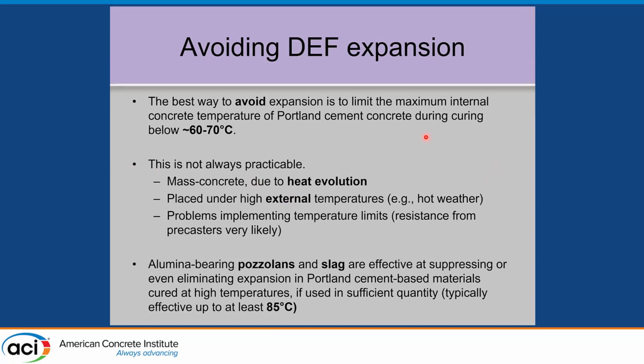So we can avoid DEF. The best way is to stay below the temperatures, somewhere around 60 or 70 degrees. Stay below those temperatures, you typically don't get the problem, but that's not always practical. In mass concrete, often you have to control heat evolution. People try and control it to lower temperatures, but sometimes they can't.